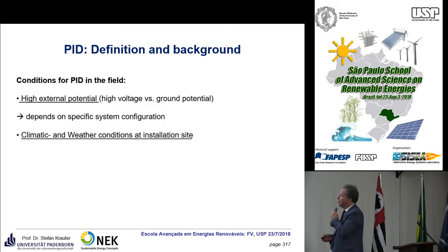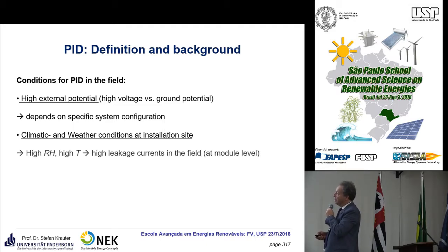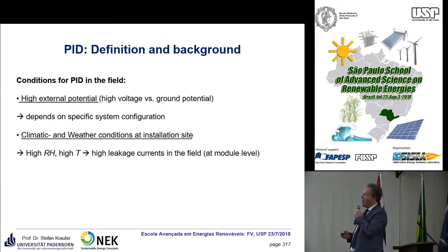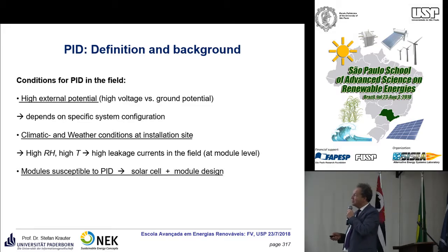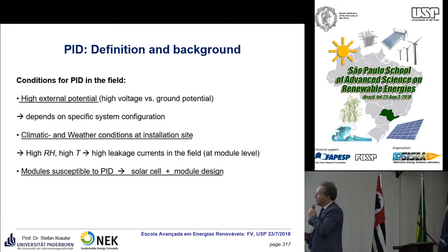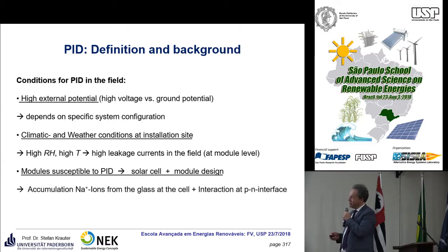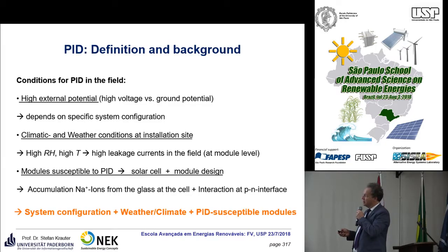It also depends on the climatic conditions, and usually these are special Brazil conditions. You have high humidity and high temperature, which lead to a high leakage current in the field, and which lead to a high PID effect. Also some modules are susceptible to PID, depending on the solar cell and the module design, others are not. There is the accumulation of sodium ions from the glass at the cell and interaction at the PN interface. So the parameters are the system configuration, the weather and climate, and the specific PID susceptibility of the modules.